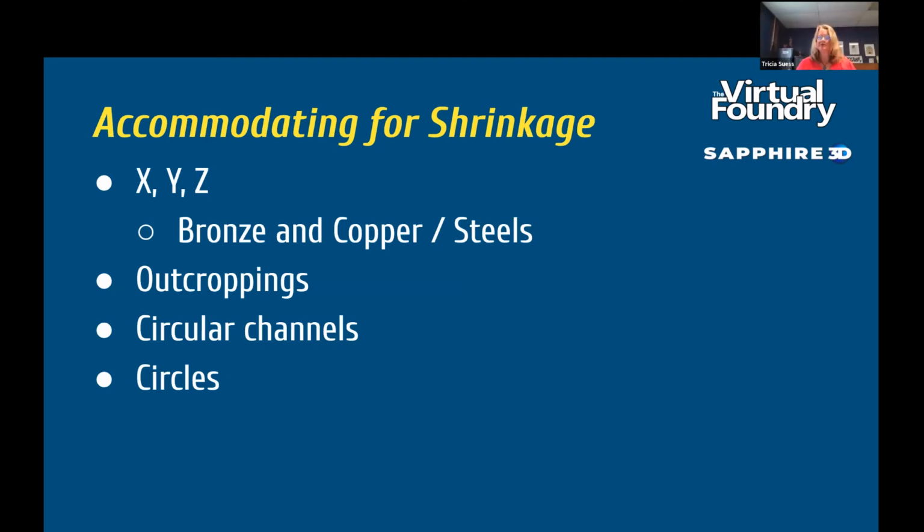And talk to us about circles. I know you've said in the past that circles hold their shape really well. Definitely when centered vertically. If you've got a tube and you make sure you fill that tube with the refractory material, they seem to come out almost very close to their design dimensions, as well as hold their shape very well.